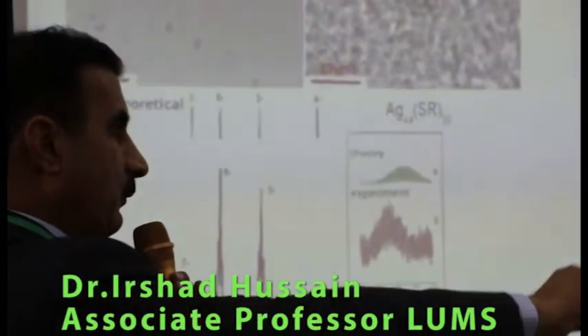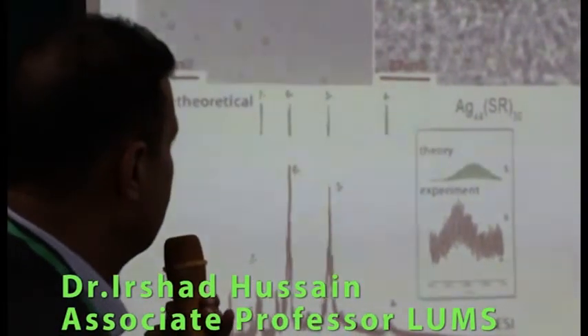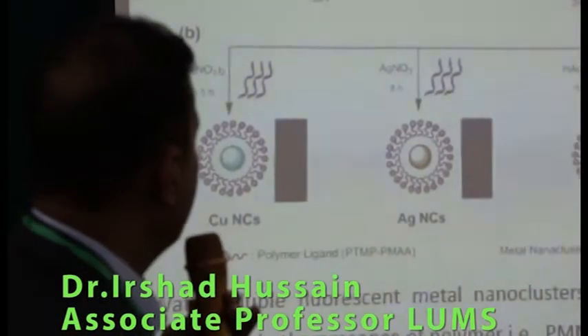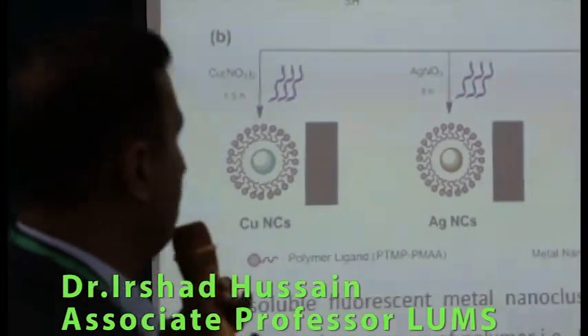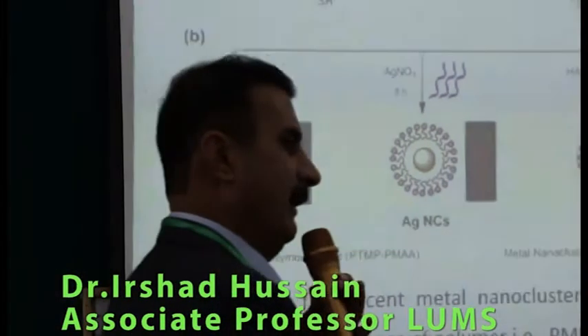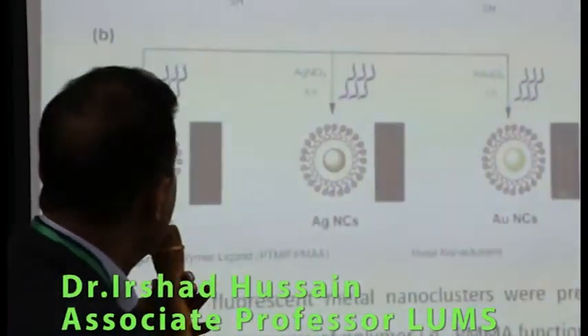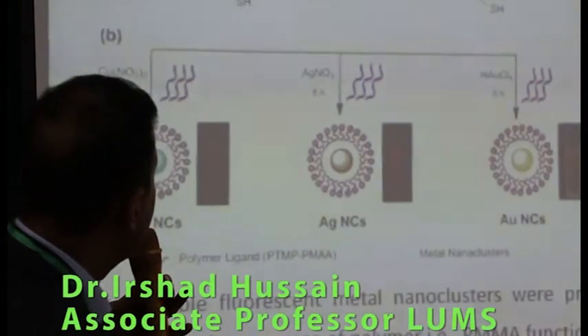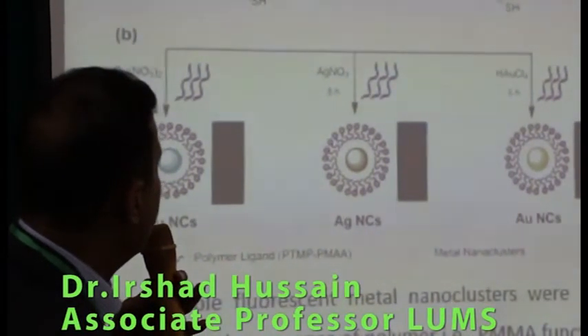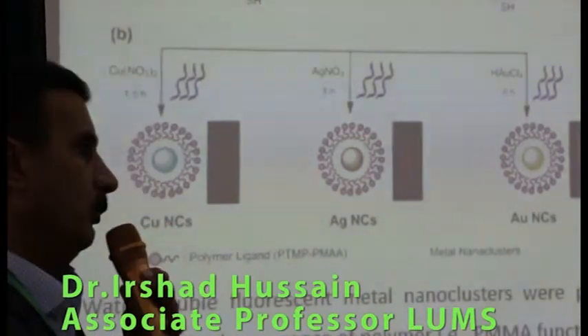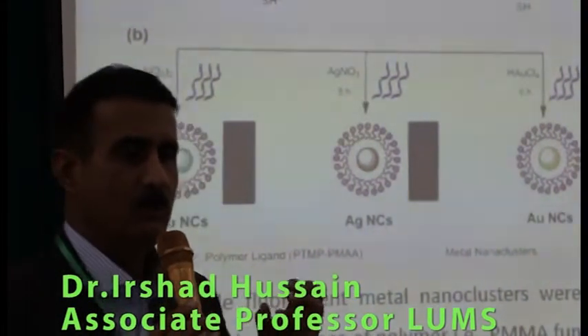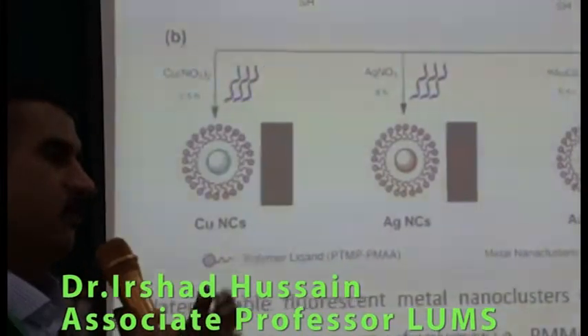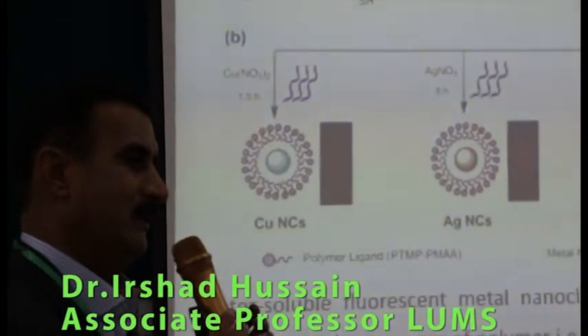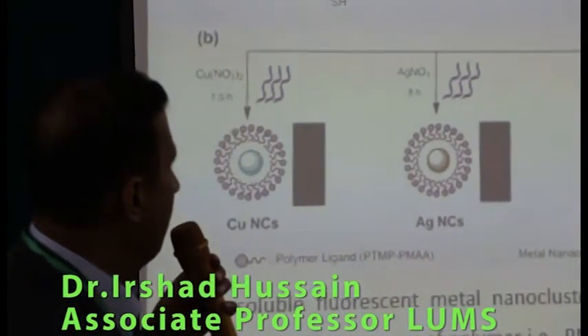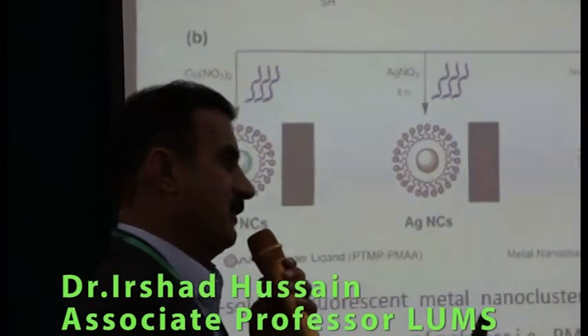So by making a very thin film of silver, that hopefully can be used. Meanwhile, we were also trying to develop many new ligands, polymer-based ligands, which basically have these thiol functional groups. One polymer molecule having several thiol groups. The purpose was to stop the growth of these nanoparticles at this early stage. And in this way, we were able to make nano clusters which were less than 1 nanometer of all these